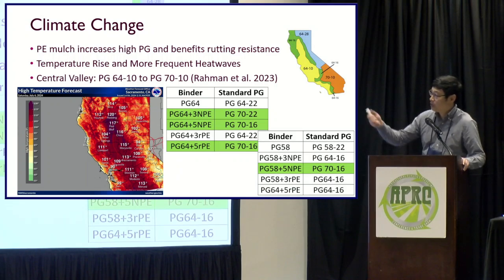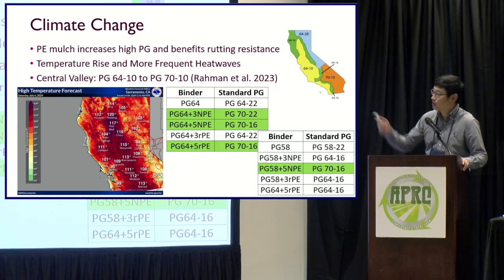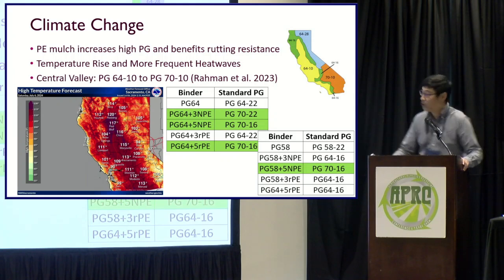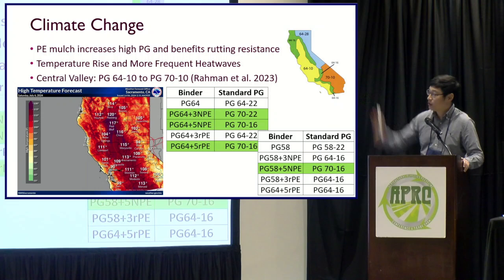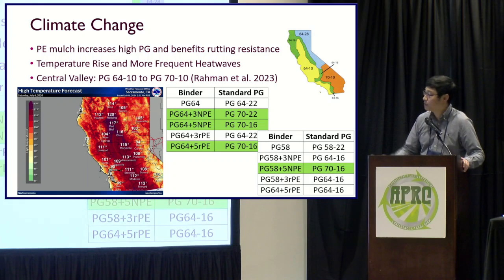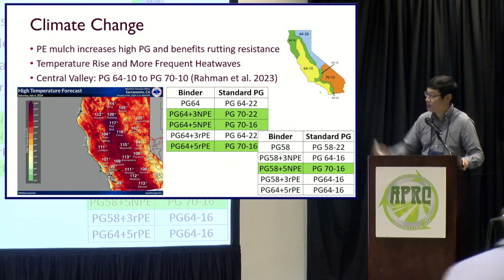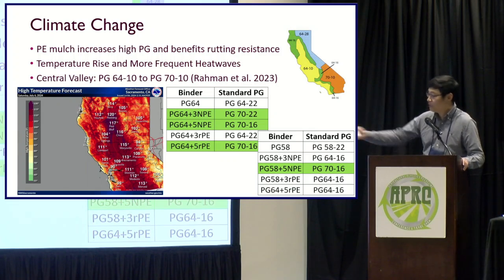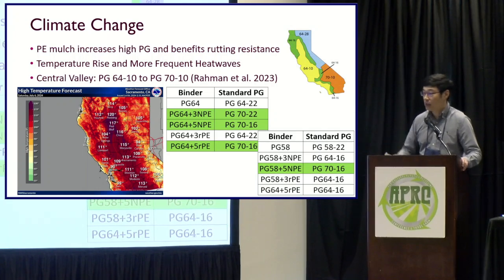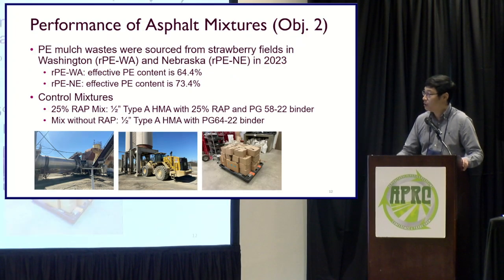the climate change. And actually, the University of California, Davis worked on the study and gave the recommendation to Caltrans for the Central Valley area, Inland Valley area, instead of using the PG64-10, due to the climate change, it's recommended to use a PG70-10 binder in the Inland Valley area, this yellow area. So if we have the still PG64 binder, we cannot use it, but when we have the plastic modified 3%, 5%, and even a lower grade like a PG58 binder at 5% effective new PE, we can use this type of binder to deal with the climate change issues in the future.